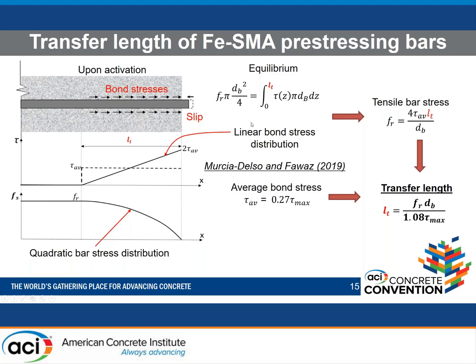Accordingly, according to this equation, and according to a linear bond stress distribution, which was recommended by Murcia-Delso and Fawaz 2019, this was an analytical model developed for conventional steel bars. It gave very good results when compared with experimental studies, and a linear bond stress distribution was found to be good in order to get very good predictions for bond strengths and development lengths. So we are using this assumption. With equilibrium and a linear bond stress distribution, we get a tensile bar stress equal to 4 tau average, the transfer length over the bar diameter.